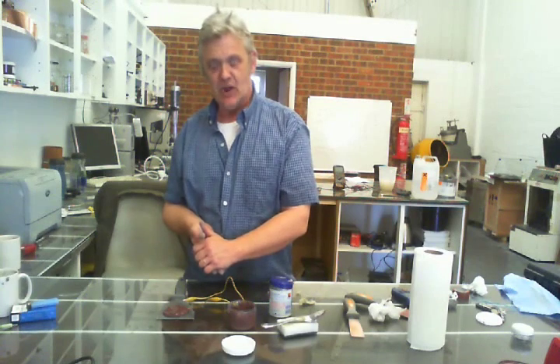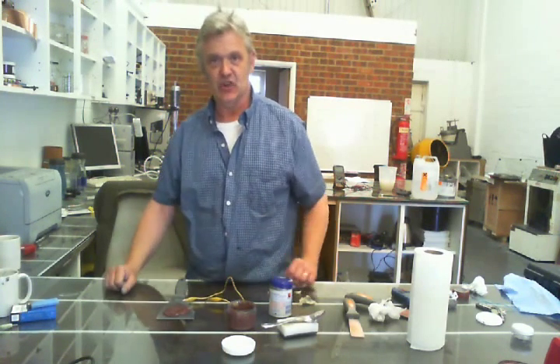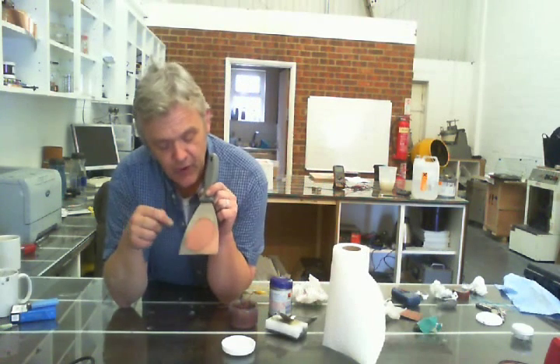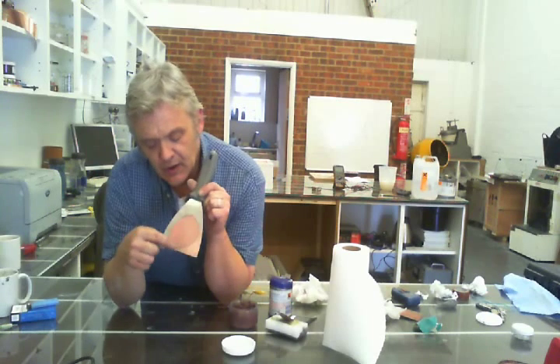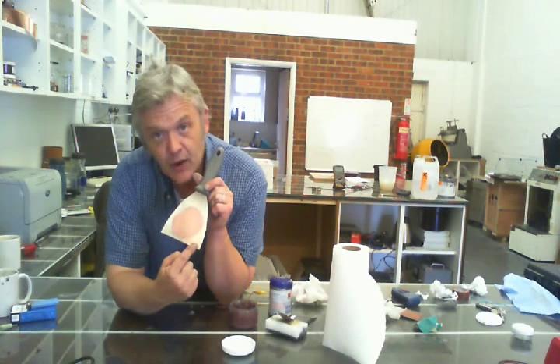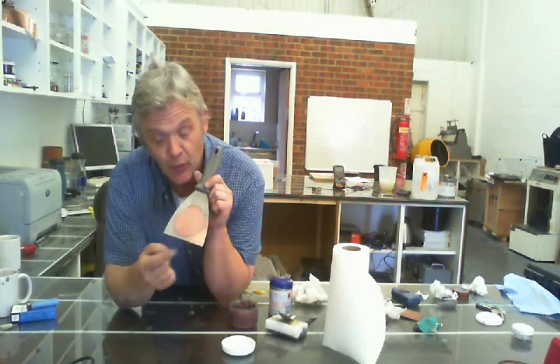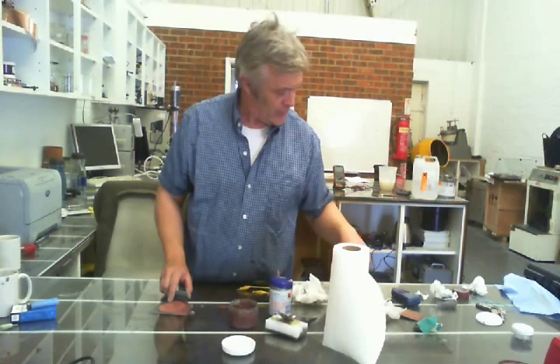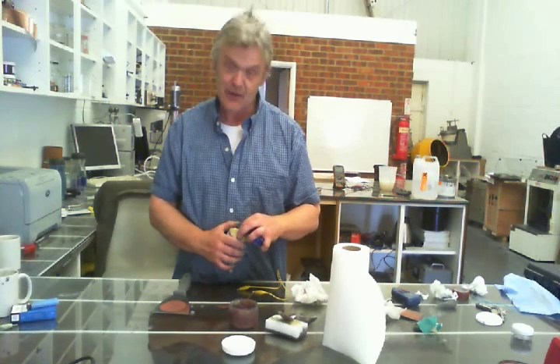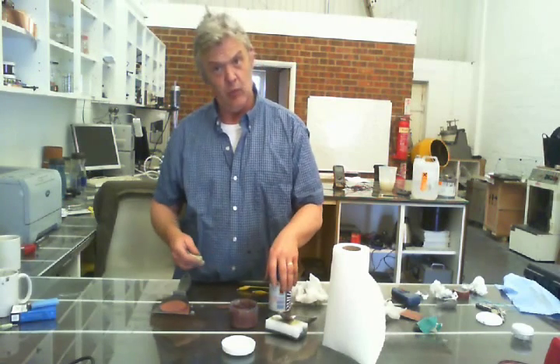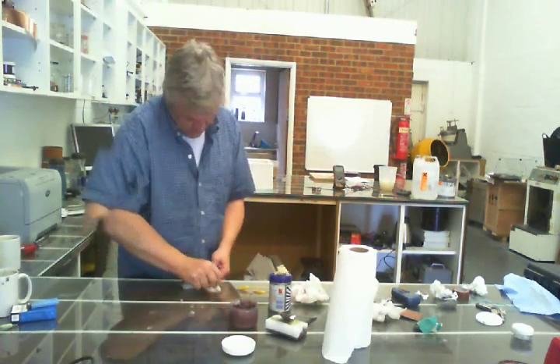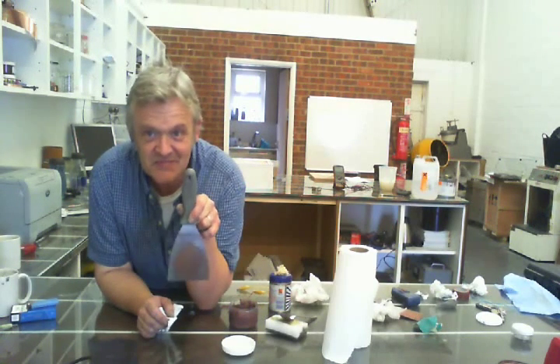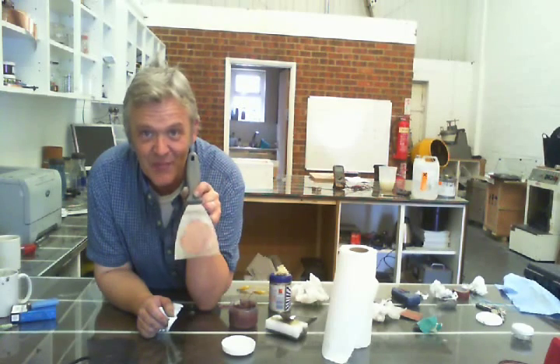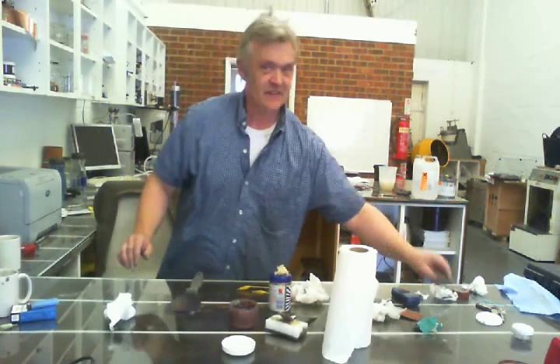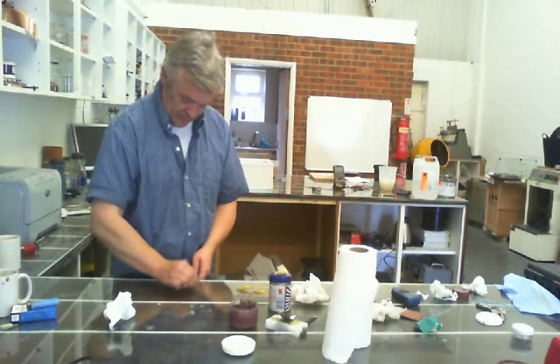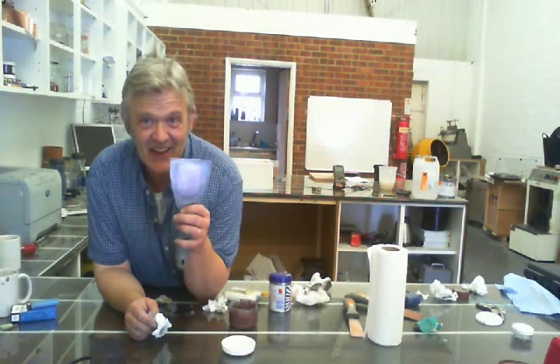So just give that a couple of minutes and then we'll dump that back in there and then clean that surface. So now we've cleaned it off, and that much deeper pink is the thicker layer of copper. That coppery colour is where I wiped it off, so it's a very thin layer of copper. Now if I can clean that up a little bit, and to be honest, you can clean it up with just about everything and anything, from a cloth to a bit of polish to a bit of wire wool actually, we'll clean that nicely. And there you go. Bright like a penny. If I take a bit of wire wool to it, there you go. Still nice and bright and coppery, and adhering very well indeed.